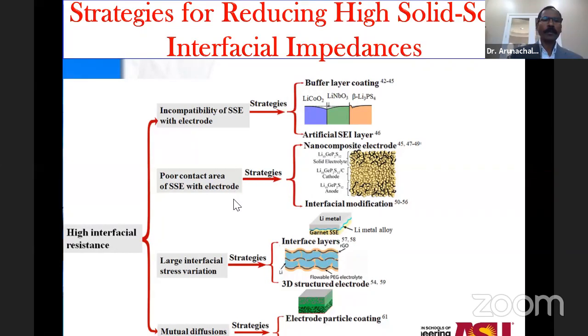And in terms of improving the contact area, you can have a nanocomposite electrode with multiple components, somehow modifying the interfacial structure with the nanocomposites. And again, you can have an alloy. So instead of just a lithium metal as an anode, you can have a lithium metal anode, and then at the interface you can have a lithium metal alloy. So mainly some kind of functional variation or gradation, not exactly with just three components, but you try to somehow soften the surface with some kind of an alloy, so that the structure becomes stable and also improves the surface area. You can see that it's not a straight line, right? So you can have a corrugated structure or any other configuration to have an improved surface area.